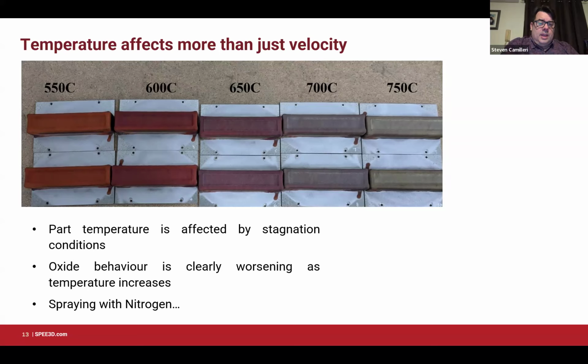Importantly, this was spraying with nitrogen and not air. We typically spray with air, but in this case, we sprayed with nitrogen. So we weren't getting hot oxygen off of our nozzle. All we were doing was heating the part up with the nozzle, and the ambient oxygen around the part, even under that nitrogen shield, was still enough to oxidize the part pretty comprehensively. So this is a note for those of you that might be wondering: spraying with nitrogen and not filling your chamber with nitrogen means your part will still oxidize. So we've got the numbers here.